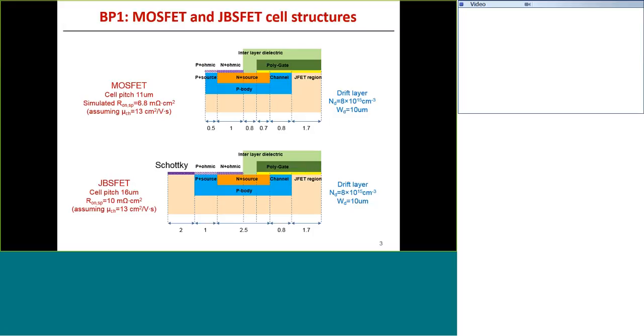If you use a Schottky contact by itself, one of the problems we encounter in silicon carbide is that you get very high leakage currents because of barrier lowering and tunneling effects. So you can mitigate those problems by using the JBS junction barrier Schottky concept. This is the concept that's already been used to make the commercial JBS diodes or Schottky diodes that are available from numerous companies. In the MOSFET structure, we create the JBS structure by using the P body region and the P plus source contact to buffer the Schottky from high electric fields. So with this approach, the cell pitch gets larger, which makes the RDS on slightly higher, but the advantages are that we have the integrated diode as explained in the previous chart.